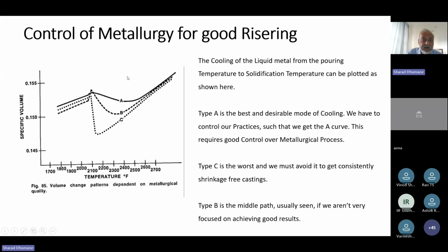This is another very important chart. Here again, specific volume versus temperature, as the sample is cooling down. I think some of the foundries must have installed this ATAS equipment, and when you pour a sample, it gives you cooling curves. This is your base cooling curve. When your cooling curve is like this, then you have minimum risk of shrinkage defects in your casting. So if your cooling curve is like this, then you have very low risk, very low probability of shrinkage.